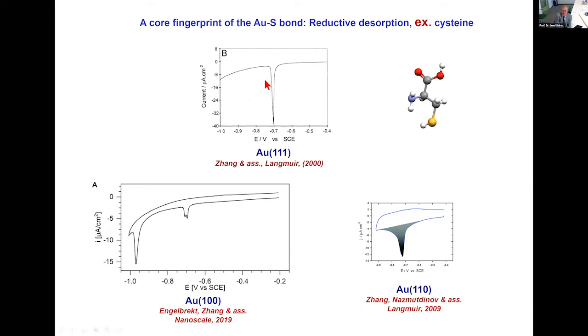You can see it's specific for the surface, gold 111, gold 110, and some recent data from our group by Christian Engelbrecht, who's sitting next to me here. There are actually two reductive desorption peaks, indicative of two different kinds of surface binding of the cysteine molecules.